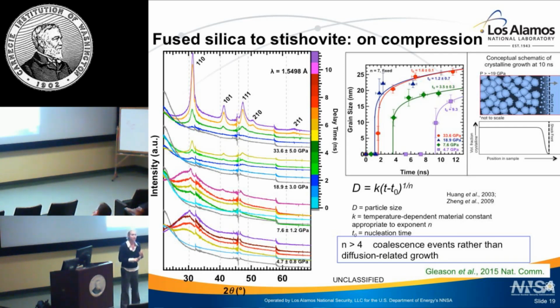I can do this as a function of time and pressure and temperature. So here I do that. Grain size is a function of time. Each color-coded trace here is a different data set. And I fit a very simple functional form to these data, wherein the grain size is proportional to time, okay? And there's a relationship here where the exponent of this functional form, this n, gives us information about the mechanism of transformation, okay?